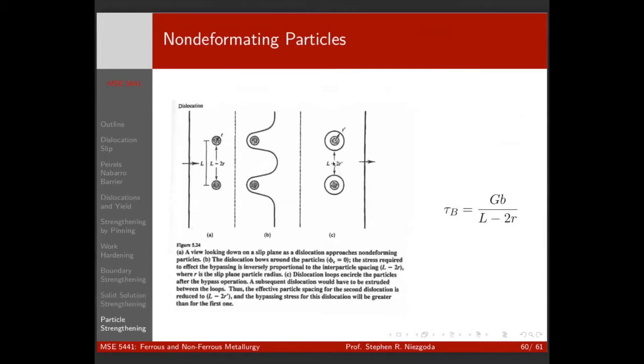You'll have to deal with the dislocation interactions. And the analysis becomes a little more complicated then, because the dislocations will be of the same sign, so you have a repulsion here, but the distance is going to depend on the force. But you can imagine after you pass a bunch of these through, and now you've got these concentric rings of dislocations around these particles, it can get quite difficult to move another dislocation through that really narrow area.